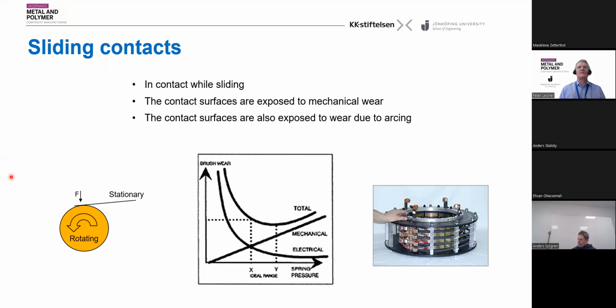So in design of such contacts, it's important to find the minimum total wear, as is illustrated in the diagram in the middle. We have the mechanical wear growing linearly with the force of the contact, but we have the electric wear due to arcing growing a lot if you have low force. And somewhere there will be a minimum which will give less wear to the contact system. To the right, you see an example of a rotating contact from a wind power station.